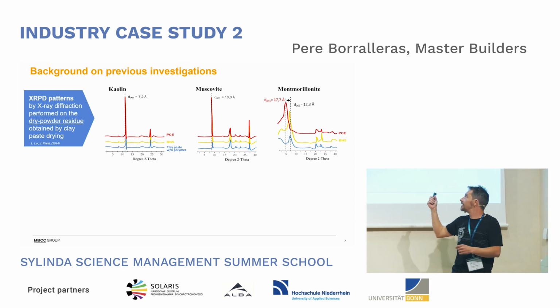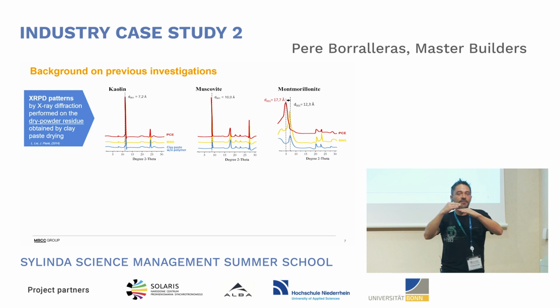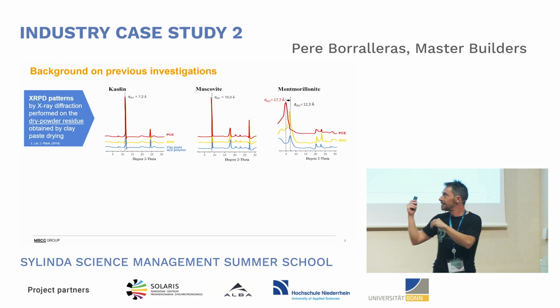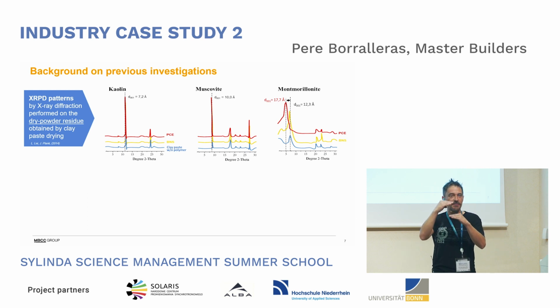But with montmorillonites, you can see that with this technology that we call PC, which I have to say is the majority today. There are different chemistries for chemical admixtures for concrete, but I would say 60% is what we call PC. And look, it was already observed by the previous researchers that the space between the two layers, when a PC-based admixture is used, expands, okay?